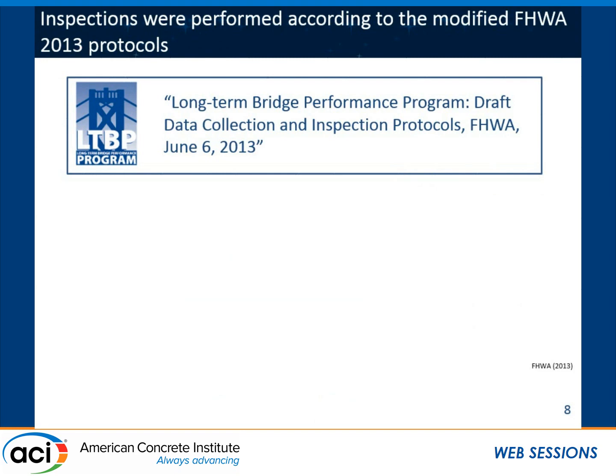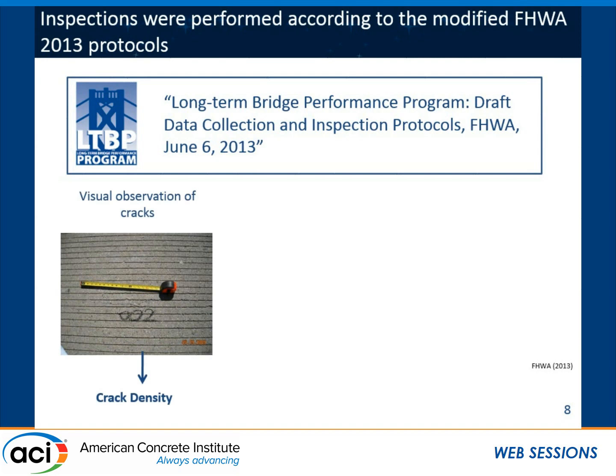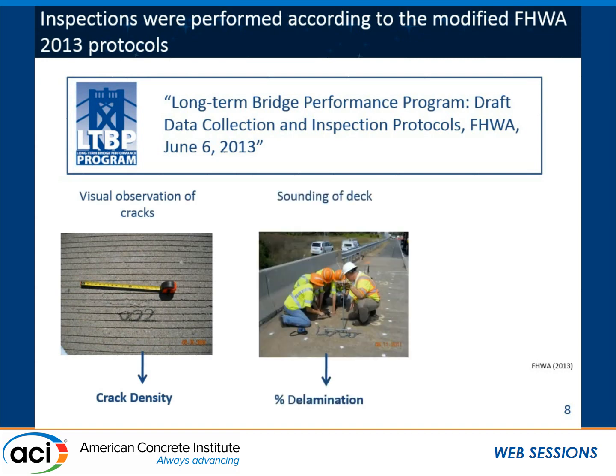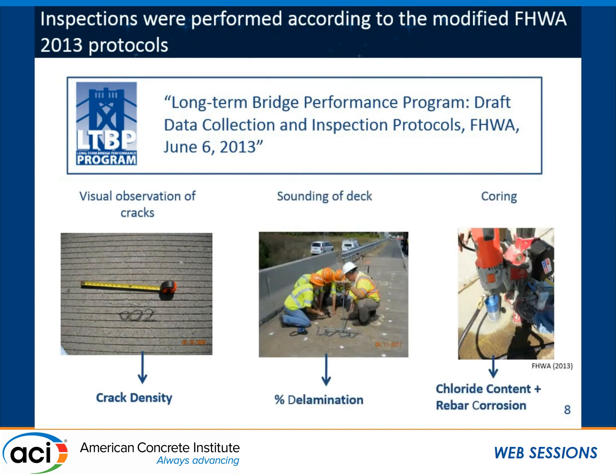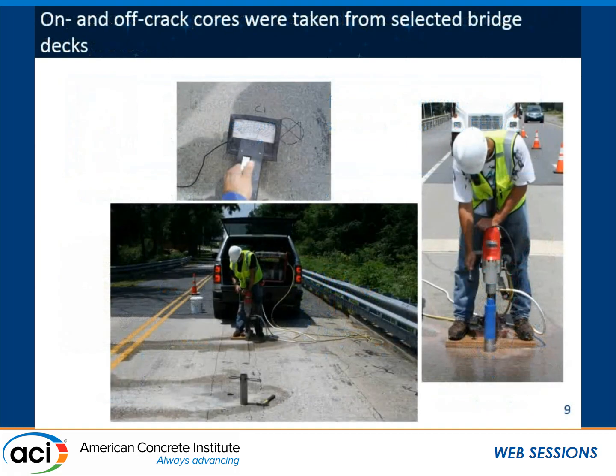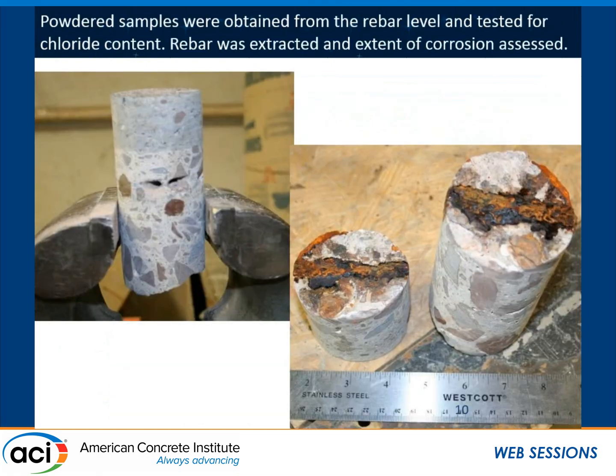This project happened in the span of 2013 to 15. We followed the Federal Highway Administration protocols that were most up to date at the time, which include measuring the crack density, measuring the delamination by sounding the deck, coring, measuring the chloride content, and looking at the rebar status. The coring happened both on crack and off crack, so we had a rebar locator that we could use to determine where the rebar is. We again took samples from the concrete at the level of rebar.